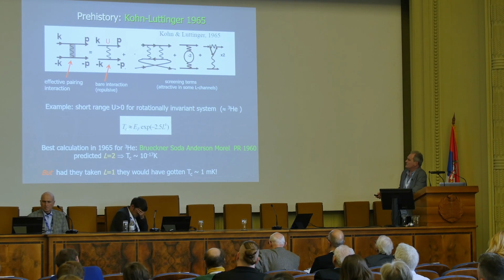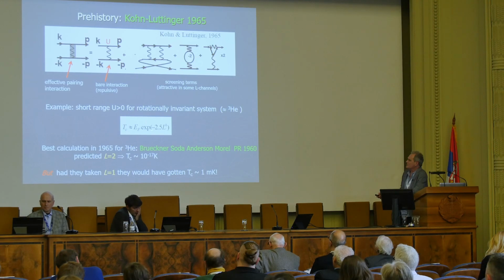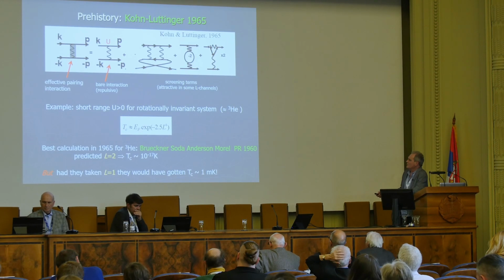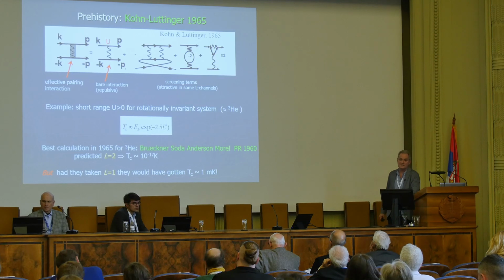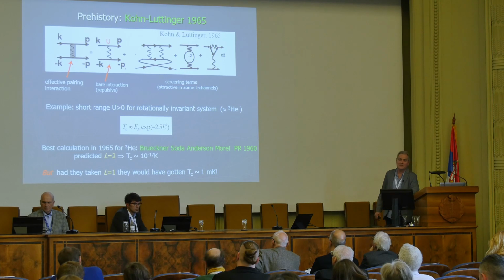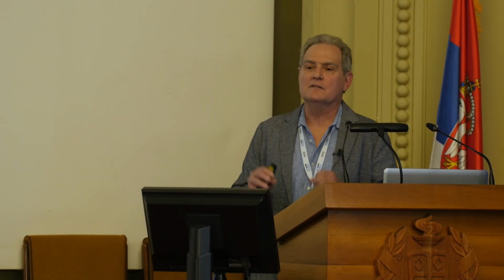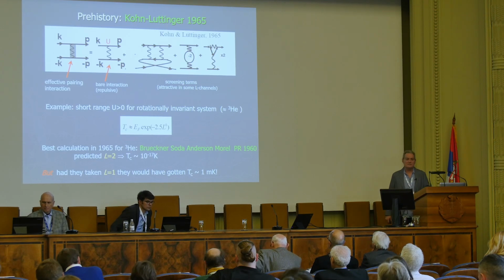And they said, okay, you get a Tc which is proportional to the Fermi energy, e to the minus some factor of order unity times L to the fourth power. That's a very big power. And if you look at helium-3, which was what they were interested in at the time, the most authoritative calculations for the potential between two helium-3 atoms said that the strongest channel of the potential, let me put it that way, was in the L equals 2 channel, the D wave channel. And so they plugged in L equals 2, and they got 10 to the minus 17 Kelvin.